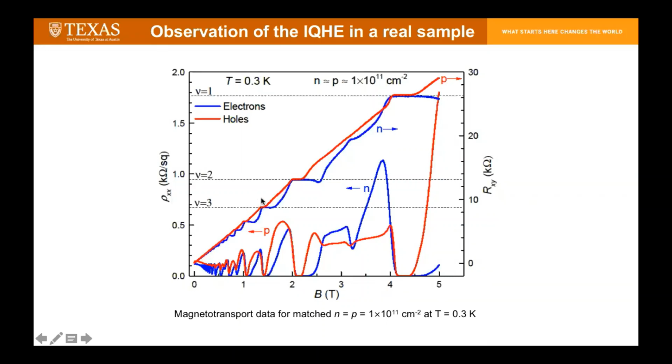So if you observe this kind of a staircase structure in the presence of high B fields in any sample, then that truly says that that sample is strictly two-dimensional. This effect is only there for a 2D sample. You don't see it for 3D samples. So this is a real test to say with surety that your system is two-dimensional.